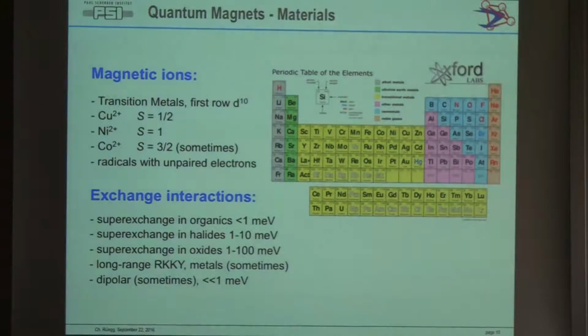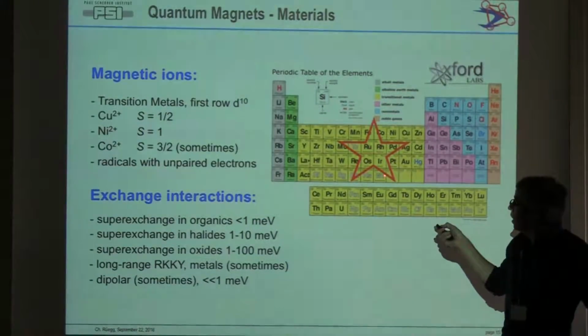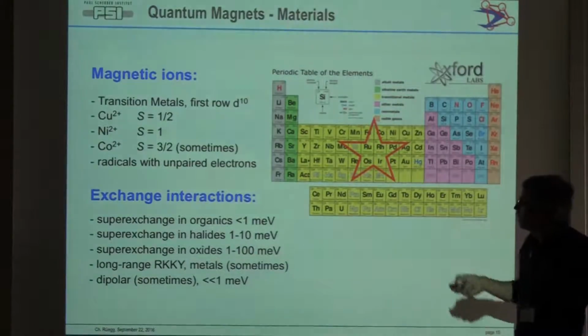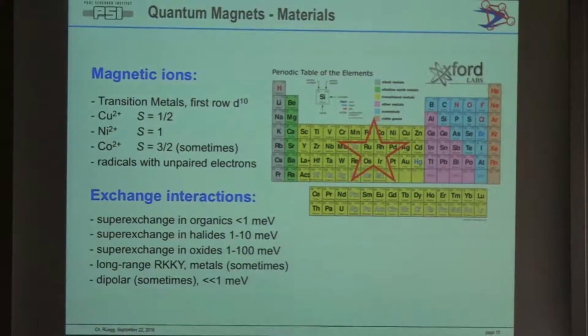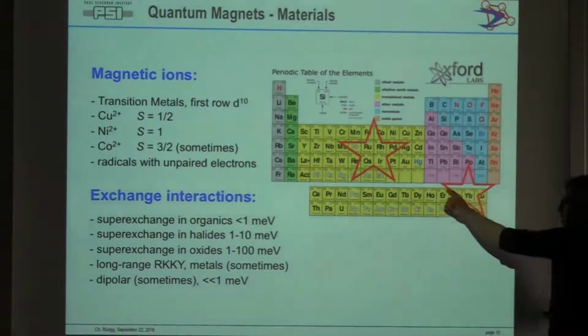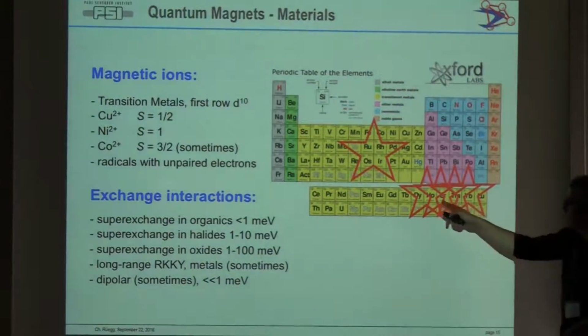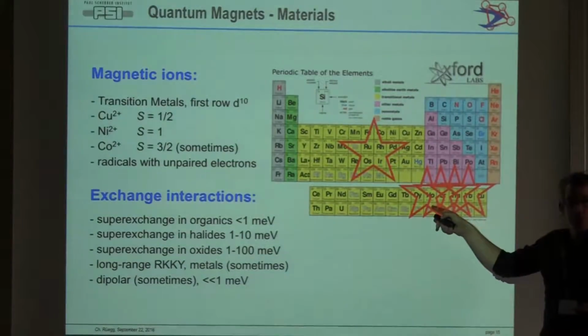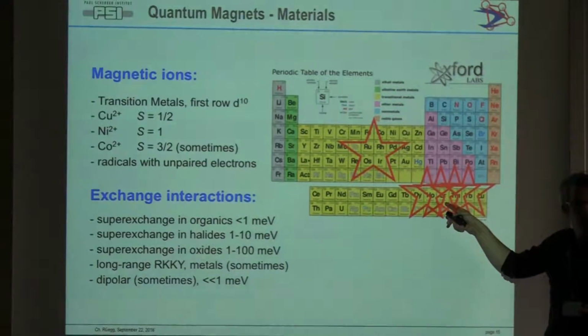But more recently, people got very interested in other systems like J-effective 1/2 systems such as the iridates. A lot of people are now working in this regime with strong spin-orbit coupling, which could be very helpful in transferring some of the excitations from the platinum into the insulating system. In some cases, people go to systems like ytterbium 3+, which is also effective spin 1/2. And we have now seen examples for XY type systems, and there you would stay down here with a rare earth, and then you get all of these. Holmium is usually a very high spin, Ising spin. Erbium is typically a very good XY system.